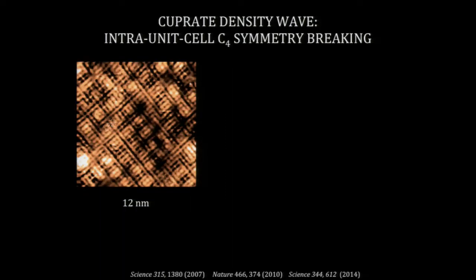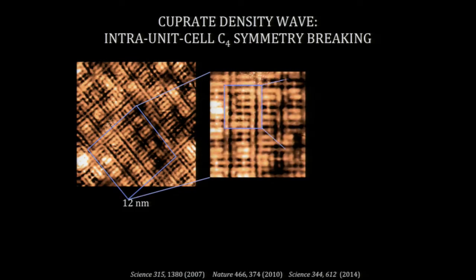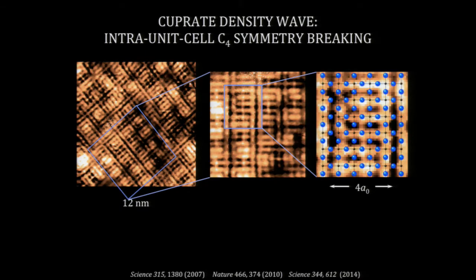Let me give you a closer look at that. So here are those ladder-like patterns. I'm going to zoom in. And now I'm going to superpose the atomic lattice. So here are copper atoms in black and oxygens in blue. And what you see, for example, in this unit cell here is that the oxygens in this direction are dark, but the oxygens in this direction are bright. So there seems to be an internal structure to this broken symmetry state. It's got a 4-unit cell periodicity, and there seems to be an internal structure to it as well.